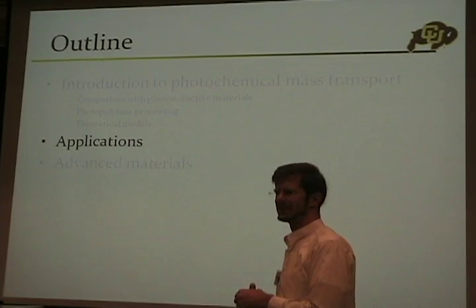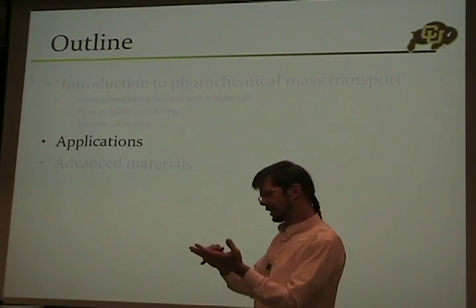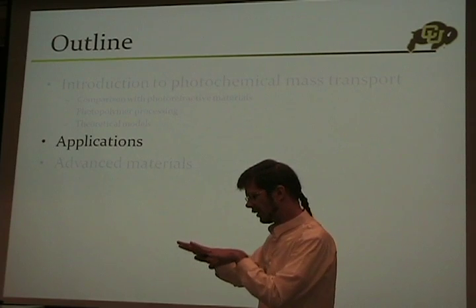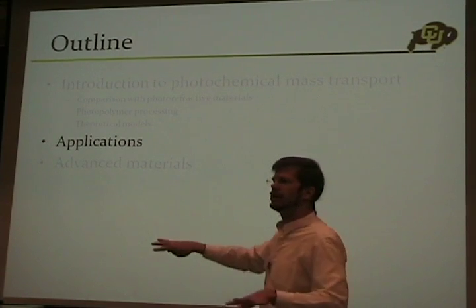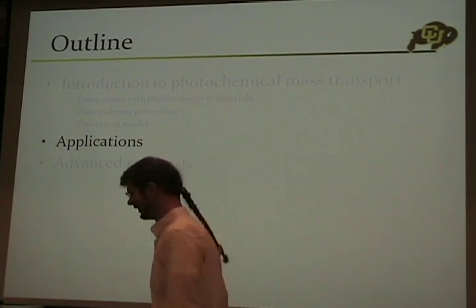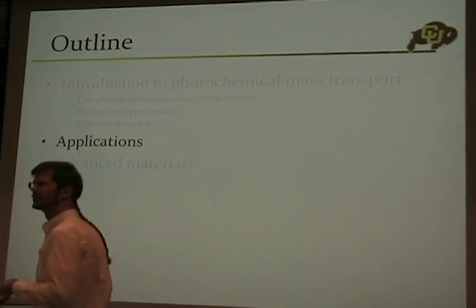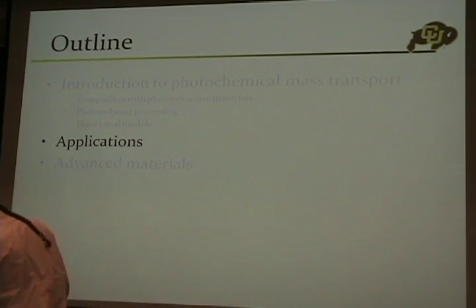That gives you knobs to reach in and try to control the three-dimensional distribution of chemicals. As polymerization continues, the viscosity goes up, diffusion slows down, and higher temperature increases both. The photopolymerization reaction is also exothermic, and if you focus down you can actually calculate — you can get 50 to 60 degree temperature rises just from the exothermic reaction locally — so you can have some local region where diffusion is much more allowed than others.